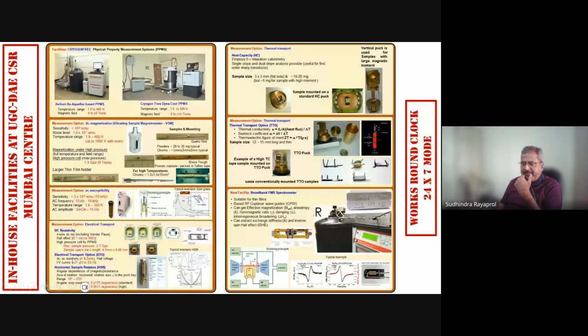We have a horizontal sample rotator also. So that means if you want to do in plane and out of plane measurements with field parallel and perpendicular to the sample surface, all those measurements are possible with these facilities. We can do thermal transport measurements like heat capacity and thermal transport, which means you can measure thermal conductivity, Seebeck coefficient, and thermoelectric figure of merit. You can calculate from all these measurements.